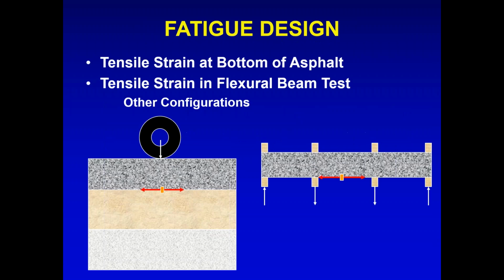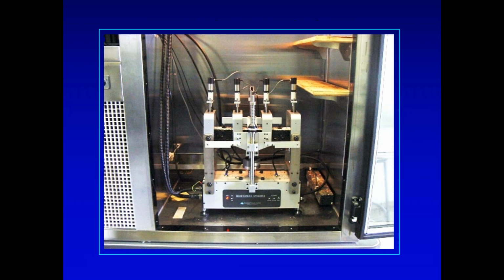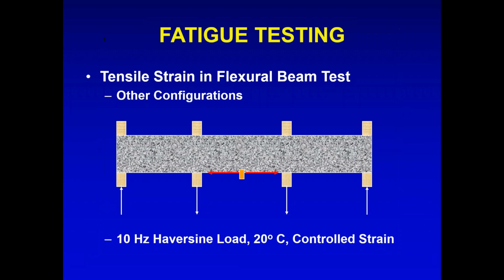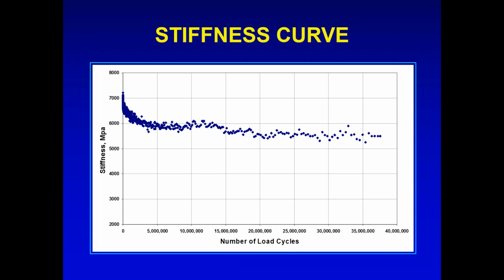AASHTO type testing, beam testing, here we go. We've got these devices in the lab, a lot of work. Tensile strain, if you look at modulus, stiffness of the beam as a function of load reps, we lose modulus as a function of load reps. Ultimately, you get down to where you get failure. Failure is typically defined as what? 50% of the original value, something like that.